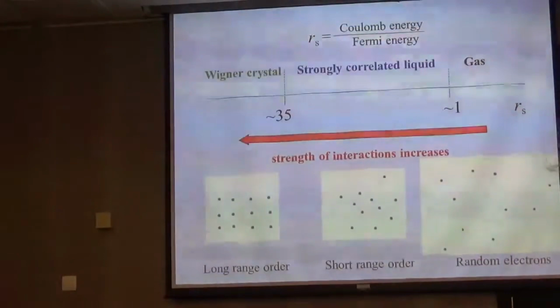They're trying to do their best to keep as far as possible from each other, right? To minimize the potential energy. So it will be either a square lattice or triangular lattice or hexagonal lattice, but it will be a lattice. And it will have a long range order. Once again, numerically it was shown that it should happen when interactions exceed Fermi energy by a factor of more than 35.